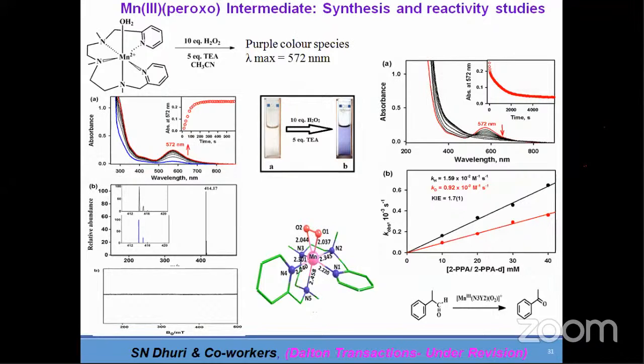Interestingly, this manganese compound was not forming the oxo species. So we thought of doing the peroxo intermediate in our laboratory. You can see here, this was a manganese(II) compound. On addition of hydrogen peroxide, something like 10 equivalents, and triethylamine in acetonitrile, the starting compound changed to a very purple, almost bluish color intermediate species in solution.